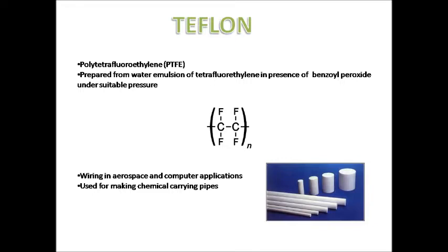The C-F bond is very strong because of the highly electronegative nature of fluorine, and it is extremely non-reactive, which gives it the characteristic of not being wetted by oil or water. And Teflon is generally obtained by the polymerization of a water emulsion of tetrafluoroethylene, which is the monomer, in the presence of benzoyl peroxide under suitable pressure.